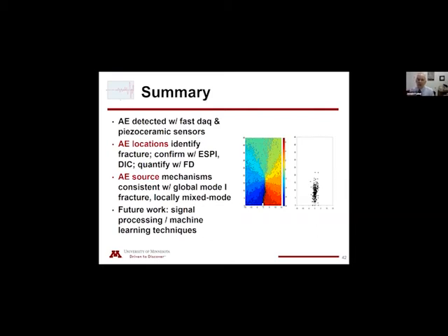And your second question is, why don't we use the entire time history? We did try it. The difficulty with these types of sensors, and I should have said it, is they resonate. They're incredibly sensitive, as I said, picometer displacements, but once they're excited, they resonate. So to get useful information, you need to clip the signal, and whether it's worth it, because this complicates the calibration procedure. We think, and others have gone this route, that we only use the information, as you point out, of the first arrival and that first peak. That's the only information we're using. So that is another limitation of the calibration procedure. Yeah, okay, thanks.